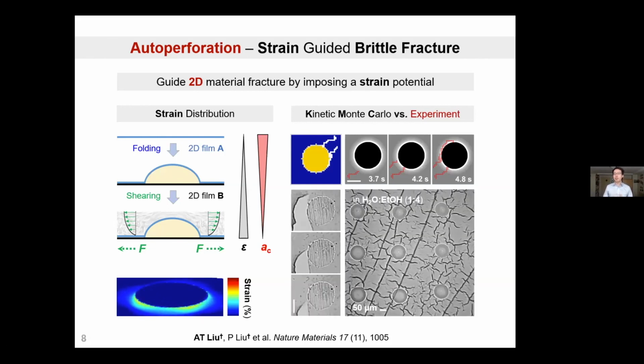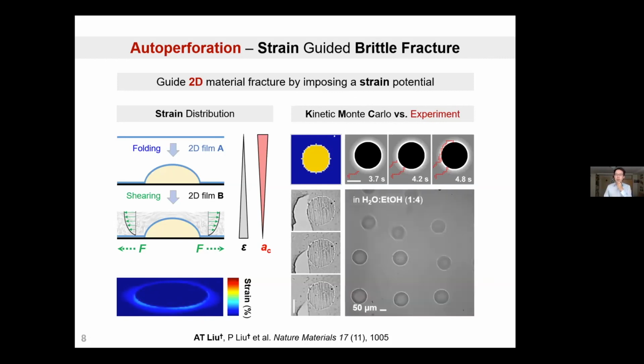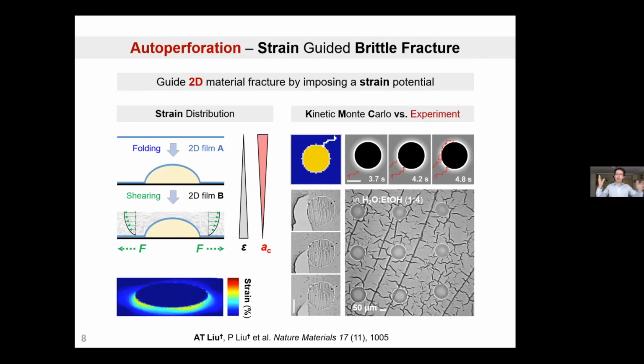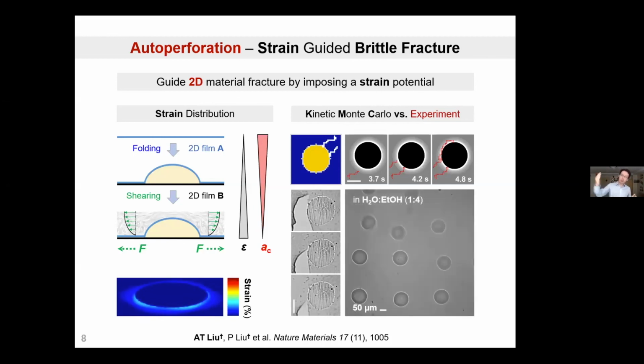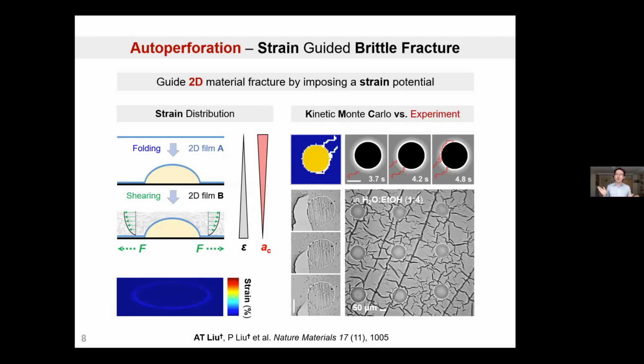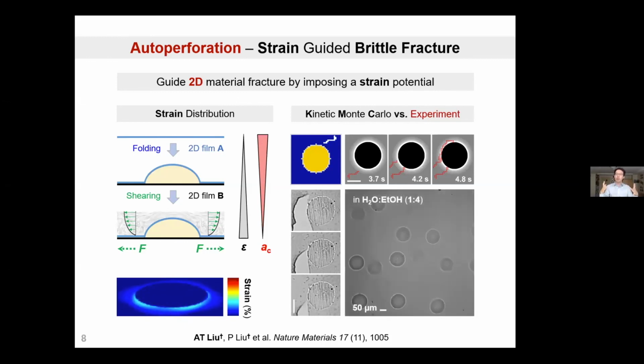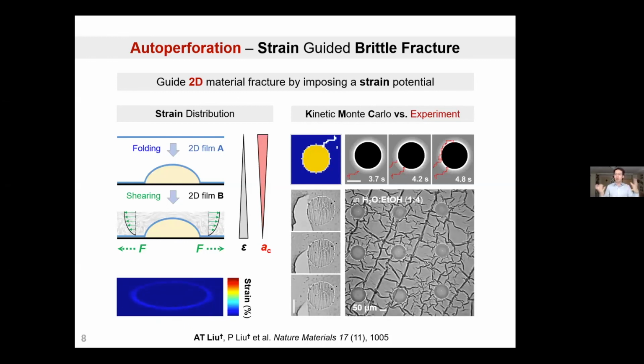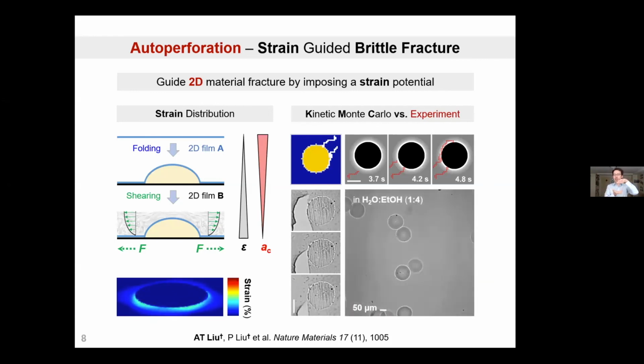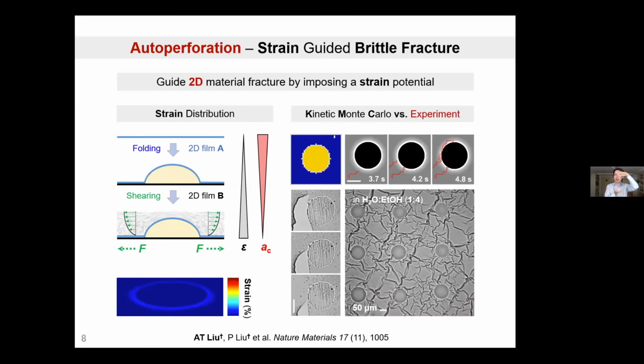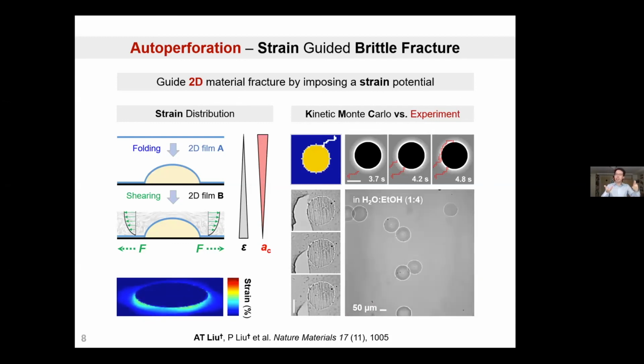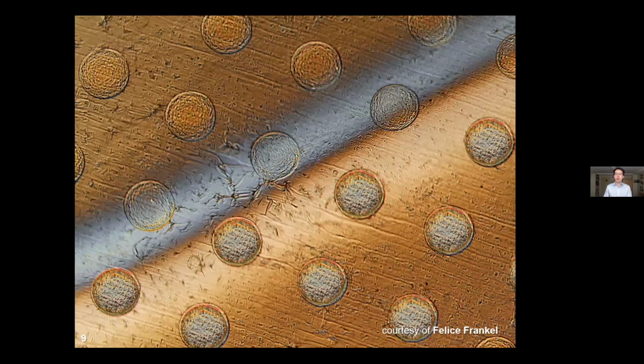Experimentally, this is very similar to what we can predict in theory. Basically, anywhere there's no support of the 2D material, it will fracture. You will see the crack propagation follow the edge of the circular pillar that we print. As a result, you get these perfectly punched out particles that are flanked on top and bottom with two layers of 2D material, just like a dumpling or a ravioli, depending on where you come from in the world. This is the kind of sandwich structure that we can make using this auto-perforation method.